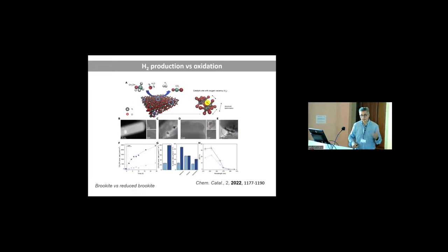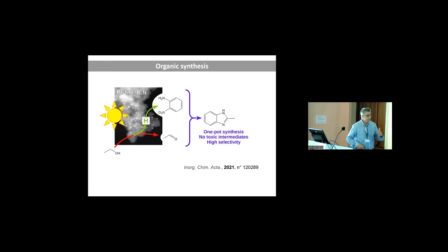Black titania is known. We have been investigating brookite, which is much less studied, and we observe promotional effects. However, the promotional effects strongly depend on the surfactant agents. People do not pay enough attention to the fate of the surfactant agents. They put methanol, ethanol, glycerol, claiming to be sustainable, but they look only at the hydrogen evolution. This recent paper highlights how important it is to look at the fate of the surfactant agent. The fate can also be involved in organic synthesis.